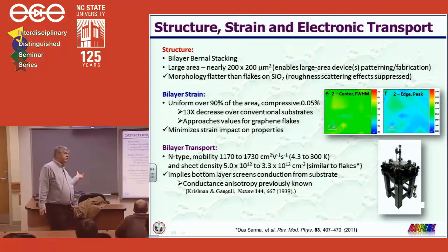We compared this. There's actually a paucity of data for bilayer graphene transport properties, but you could find in the Das Sarma review a compendium of that data. And it's within like 20%. Considering that the flake data contained in the review was based upon samples on the order of 5 or 10 microns, and this is a 200 micron mesa, the agreement is remarkable.